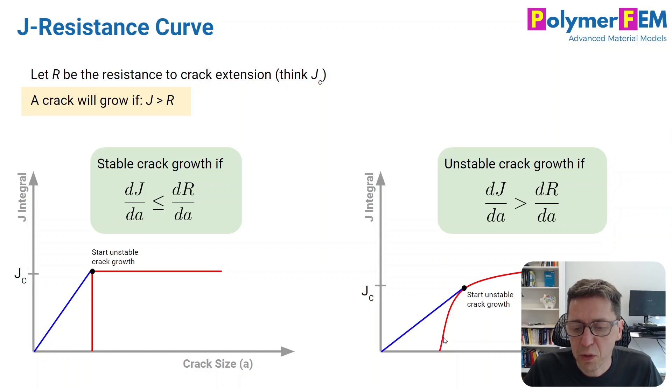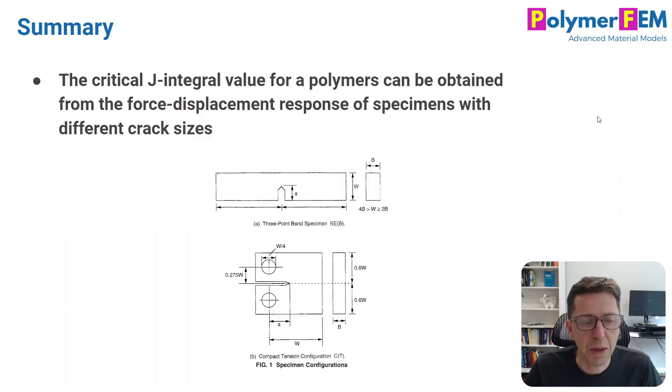In this case to the right, it's more realistic for ductile polymers and other ductile materials. We have a slope that's not absolutely vertical. What happens here is the crack actually blunts a little bit initially and that gives you that shape. But there's stable growth of that crack's length until we reach an unstable condition. These are things you can measure and this is how it applies.